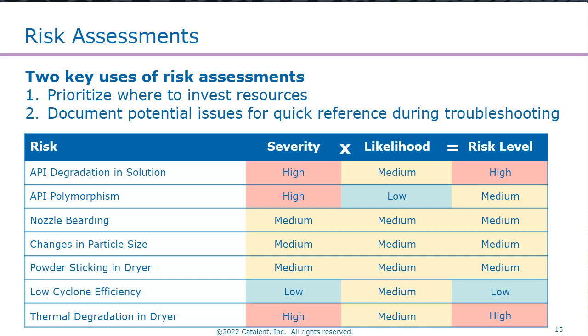Some high-risk examples would be things like API degradation in solution. This could cause out-of-spec product which couldn't be released, so we need to have a high degree of control over things like this. A lower impact example would be low cyclone efficiency. The severity of this is usually low, provided that we can still meet the clinical supply, and the likelihood is medium. Usually at this phase, we have a good understanding of what is driving our yields, and we can control it. So in this example, we would spend more of our effort making sure our API doesn't degrade in solution versus worrying about our cyclone efficiencies.